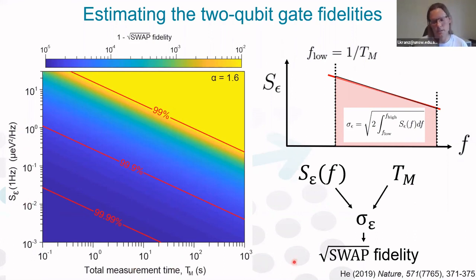And this modeling is done just by time evolution of the Hamiltonian of our two-electron spin system, and we take into account detuning noise, and we compare it to the case with no noise whatsoever, so the ideal square root swap gate. And then by comparing these two, we can get an estimate of the two-qubit gate fidelity. So this gives us an upper bound of achievable two-qubit gate fidelities given this integrated noise.